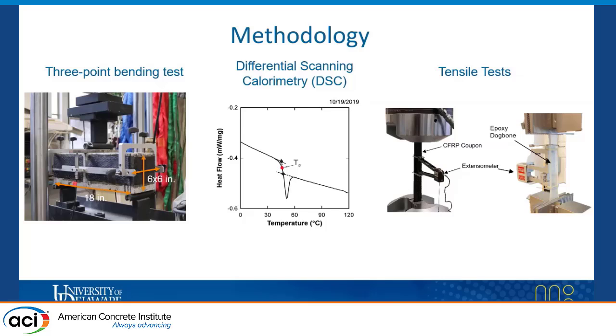The strengthened beams were small scale concrete beams. They were 6 inches wide by 6 inches high and had a span length from support to support of 18 inches. Those beams were tested in 3-point bending in order to assess the durability of the carbon fiber splay anchors. Epoxy and putty were both tested using DSC to classify their glass transition temperature. And CFRP coupons and epoxy dog bones were tested in tension for their mechanical properties.